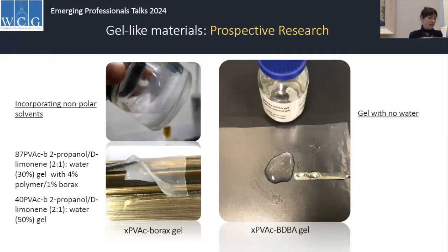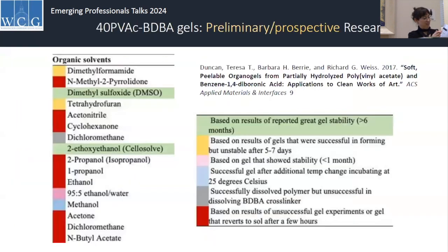So that's very interesting. The xPVAc-BDBA gel, I have actually just started working with, and I've done some preliminary experiments with these, and I found that they're actually more sensitive than the xPVAc-borax gels to differences in components and the ratios of those. So I feel like there's a sweet spot that we need to hit depending on what we're trying to formulate and what we're trying to put in that system. And I might just go next slide, actually.